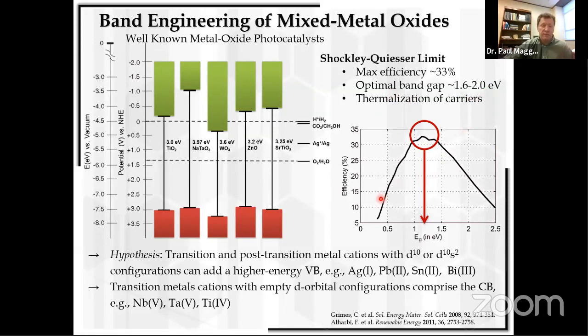And so to drive this research in the direction of more efficient metal oxides for these reactions, our hypothesis, at the very beginning when I started here, was including transition metals with filled d10 and d10s2 orbitals, such as silver 1+, lead 2+, tin 2+, which would add in those filled energy levels within the electronic structure and shorten the gap. Now, of course, we have to keep the connectivity of the early transition metal as well.